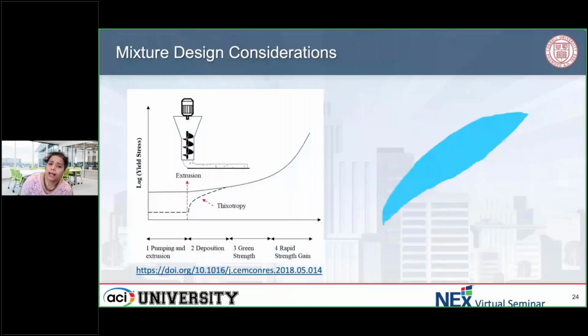So this is from this paper, I have citations. We can see this is the log of the yield stress. So this is like if you were to do a rheology test and measure the yield stress of the material. During pumping, you want a very low yield stress. But during deposition, you want this transition to be really quick.